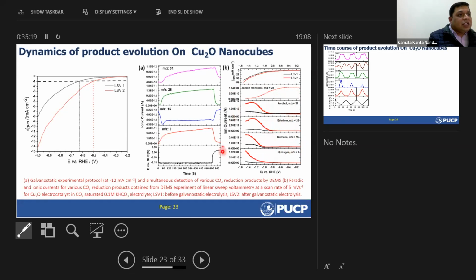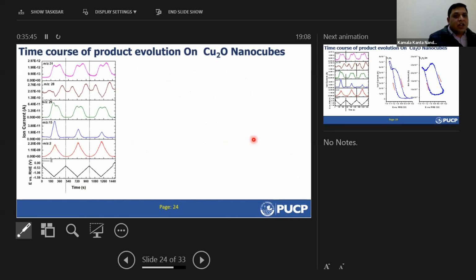And here we can see from the nature of the onset potential that alcohol and ethylene formation occur via a similar mechanism, as they have a similar shape of the curve and similar onset potential. And on the other hand, methane formation has a different onset potential and different shape of the curve, therefore it occurs via another mechanism. Okay. Further, we did cyclic voltammetry, and we could identify here that the copper surface is changing during the electrocatalysis.